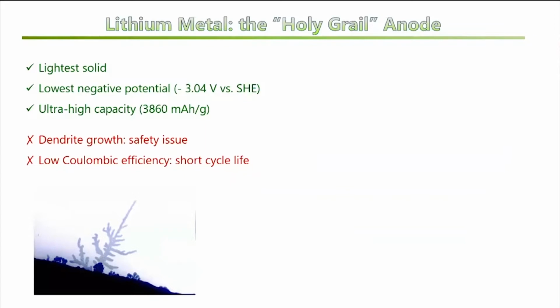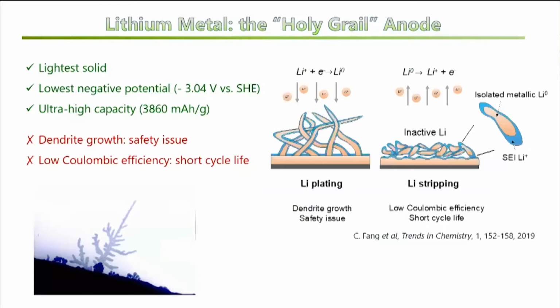And it also has the ultra-high capacity that is more than 10 times higher than that of graphite. However, because lithium metal is so reactive, it has a lot of problems in practical application in a battery. During the charging process, the lithium can easily grow as dendrites, which can cause short circuit and explosion of our battery. And during the discharge process, because of the formation of so-called inactive lithium, the cycling efficiency can be very low. So the cycle life, you can only cycle your battery for at most 100 cycles.